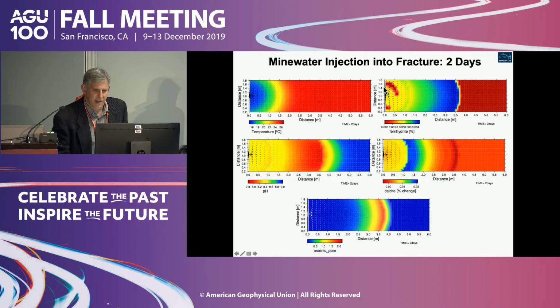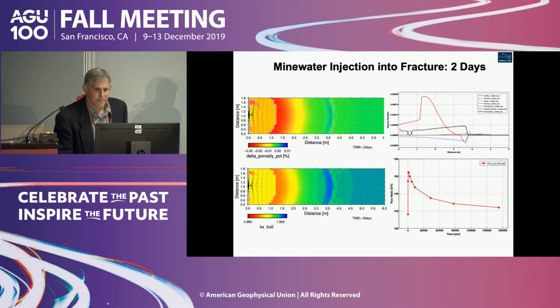And if you look at ferrihydrite, it's actually forming out at this front. Calcite is forming in this region, but it's dissolving out at this lower pH region. So you're getting this front of differing bands of mineralization happening in the plane of the fracture. And just as you're dissolving arsenopyrite, you can see where the arsenic is growing, and it's kind of being pushed along with this front as well.